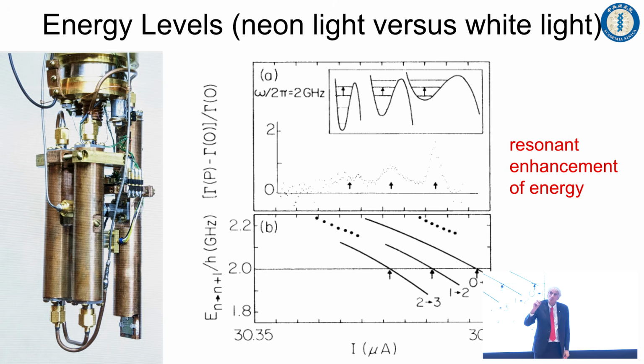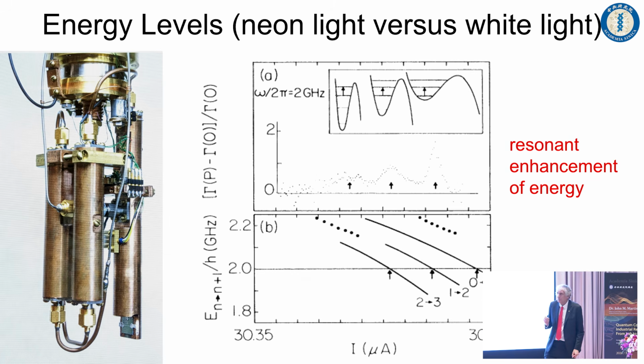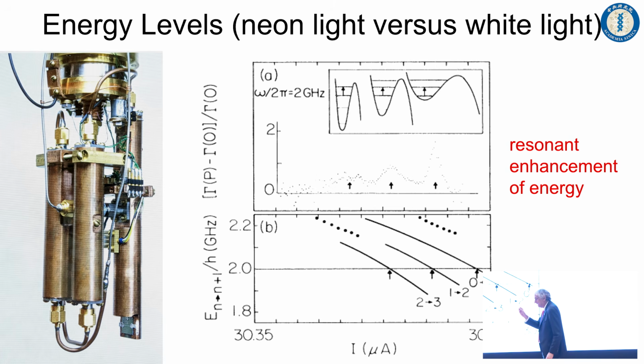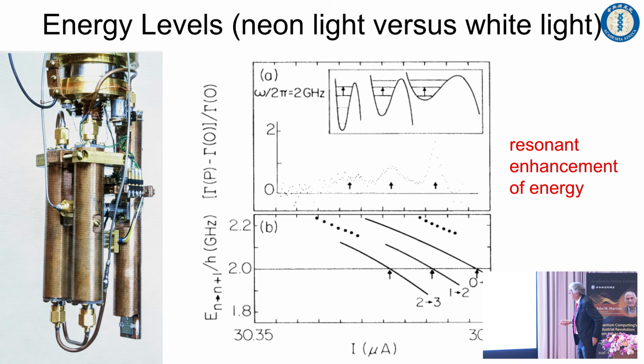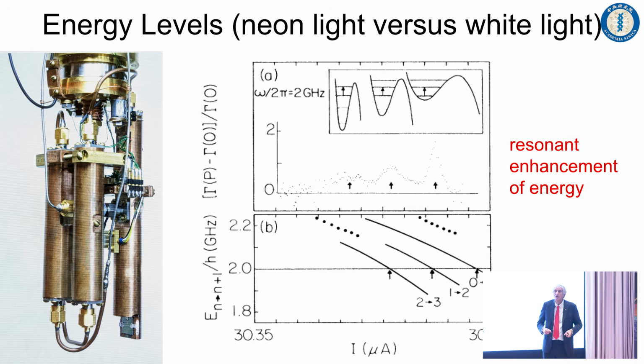So this is actually when quantum mechanics was discovered and started to be understood. This was very surprising in the beginning. Why do you have these distinctive frequencies coming out? And it's because the light comes out in quanta, in certain energies. And that's what you look for to absolutely make sure you see quantum mechanical behavior. So what happened here is we measured the escape rate, which is this gamma, when there was no microwave power versus current here. And then what we did is we measured when we put on some microwave power. In this case, it was 2 gigahertz. So if you add some energy into the system by pushing it with microwaves, you expect the escape rate out of the 0 voltage state to the voltage state to be enhanced. You're pumping energy into it. And that's what you see.